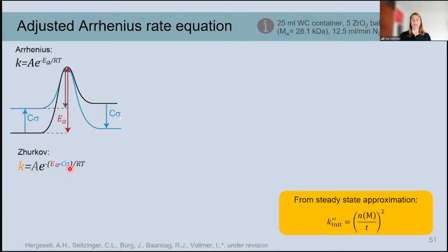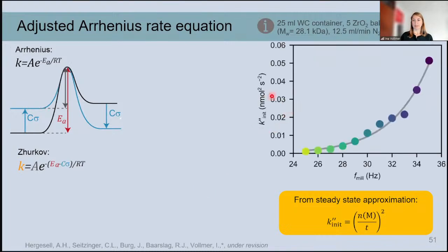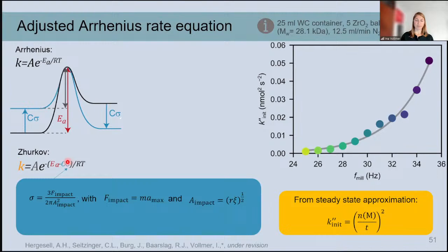And so what we need for that first is to get this k. So with the steady state approximation that I also explained earlier, we can calculate that the rate of monomer formation squared is this rate of radical formation, which is actually what we describe here. So the carbon-carbon bond cleavage to the radicals here on this side. And so if we plot this radical initiation rate on the y-axis and the milling frequency on the x-axis, we get this relationship. And then we need to have a description of the sigma, so the stress on the polymer.